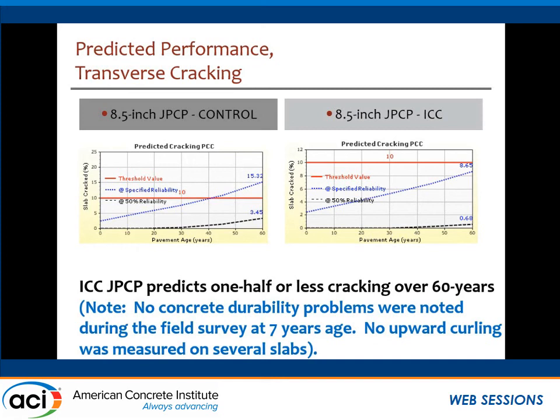So when we modeled this pavement, we're showing you the control and the ICC sections here. On the x-axis is plotted the age, and on the y-axis you have the development of slab cracking. Over a 60-year analysis period, in the control section you're going to get about 15% cracking at the end of 60 years, but you're getting just about 8% cracking in the internally cured concrete. And usually the criterion is about 10% for slab cracking. So that's a theoretical verification for the observed performance on the pavement.